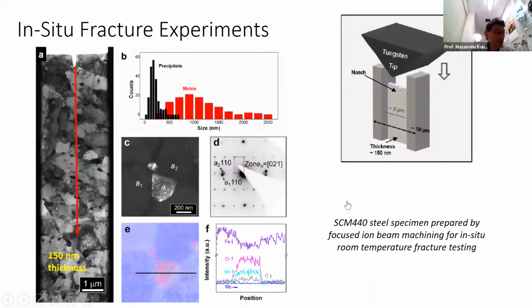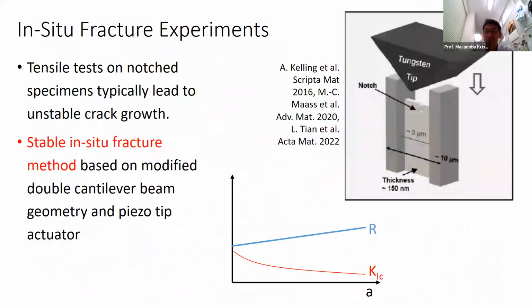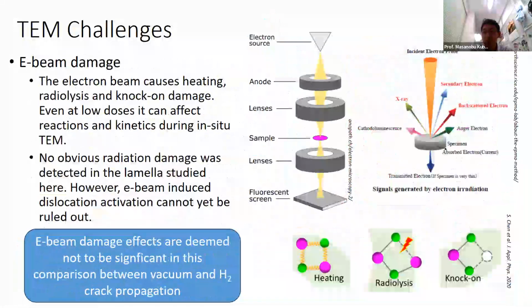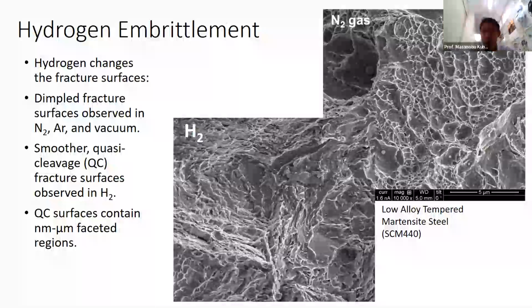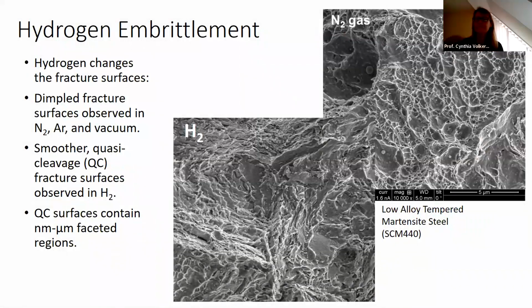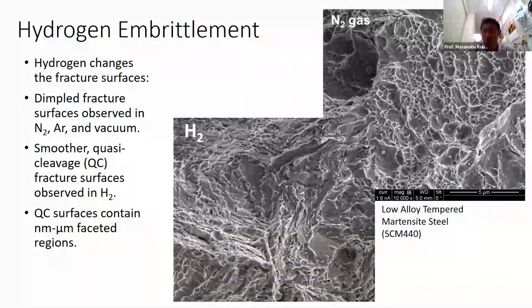Okay, and another question. Does anybody have any questions? Petros observed, beneath the fracture surface created in the presence of hydrogen, by the pick-up TEM technique. Site-specific TEM, a combination of FIB plus TEM. Right. Petros observed very significant evolution of dislocations beneath the surface in the presence of hydrogen. So do you have any common feature with their observation in your experiment?